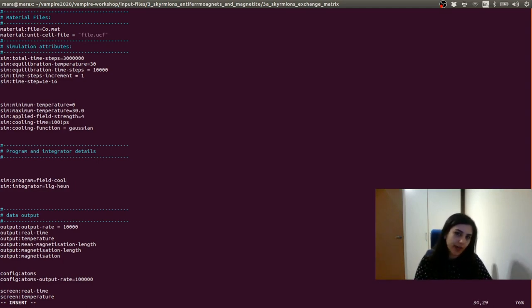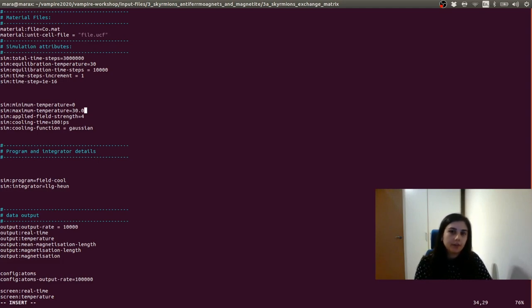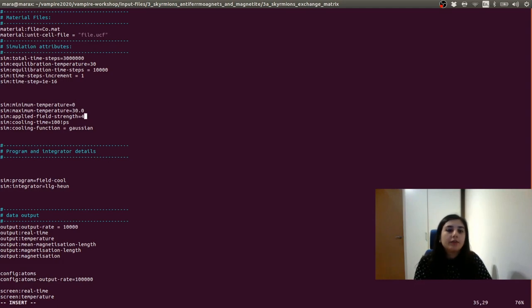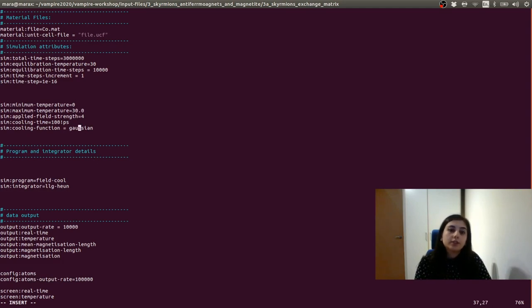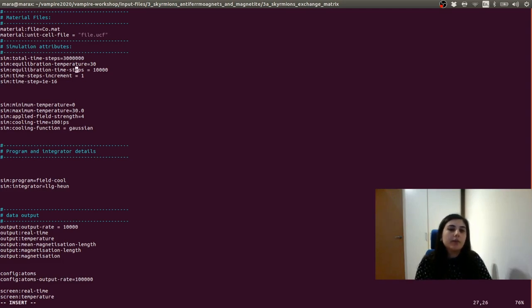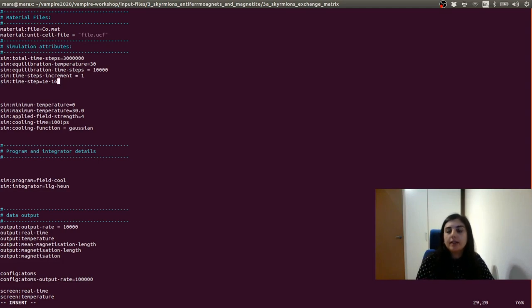For the exchange interaction we have used in our simulation, the Curie temperature is quite small — after 30 Kelvin we are already in a paramagnetic state. The minimum temperature goes to zero to see the ground state of our system. We apply a four Tesla field and cool for 100 picoseconds using a Gaussian cooling function, going from 30 Kelvin to zero Kelvin following a Gaussian shape. We set up the total simulation time to 300 picoseconds, then do some equilibration at 30 Kelvin for about 10,000 steps. We use a small time step of 10^-16 because we have this kind of chiral structure that needs more precise integration.